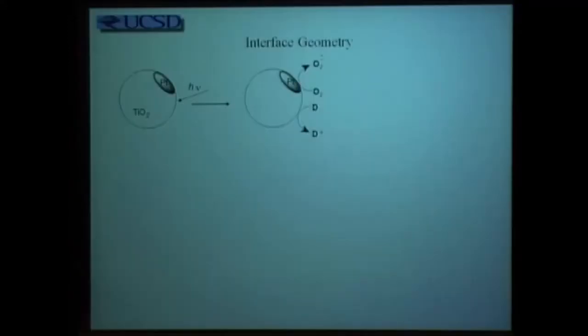Here at the far left is the TiO2 with a small platinum island, the one that we found so effective for both destroying pollutants and for doing chemical oxidations. To its right, you can see that oxygen is reduced to superoxide, and any donor molecule is oxidized to the corresponding cation.